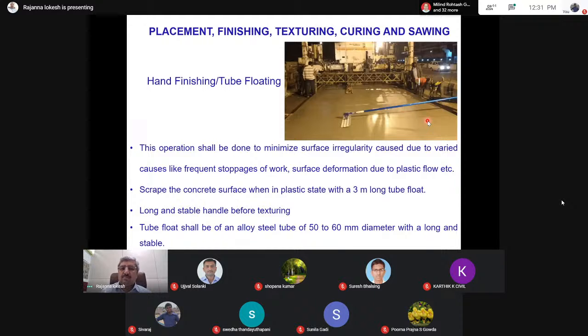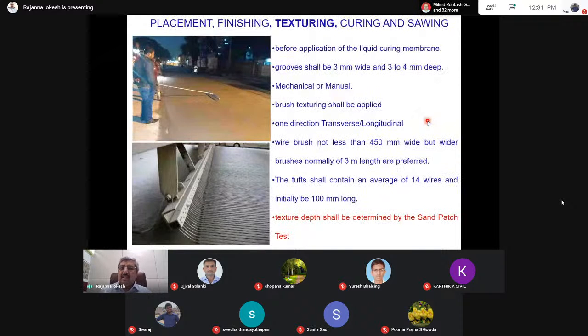undulations could be reduced. And next is texturing. Before the application of curing, it is important for us to do the texturing. The texturing will be done with a 3 mm wide groove for a depth of 3 to 4 mm.